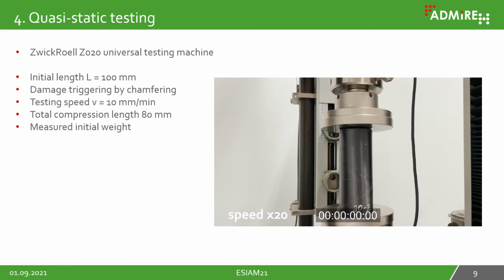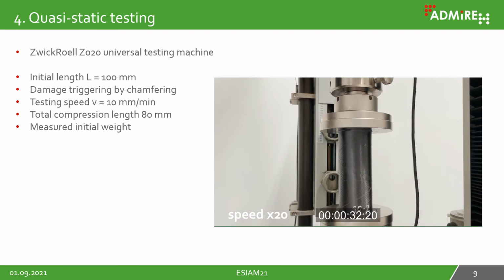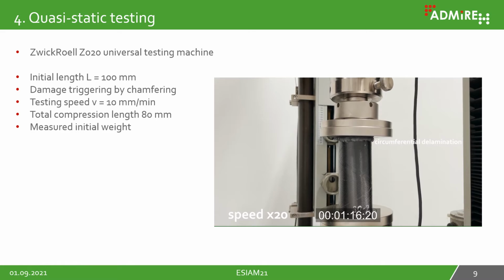For conducting our quasi-static testing, we used our ZwickRoell Z020 universal testing machine. The crash tubes had an initial length of 100 millimeters, and for damage triggering, we chamfered our crash tubes at a 45-degree angle. Before crushing the continuous carbon fiber tubes, their initial weight was measured. Tubes were then compressed at a speed of 10 millimeters per minute for a total crosshead displacement of 80 millimeters.